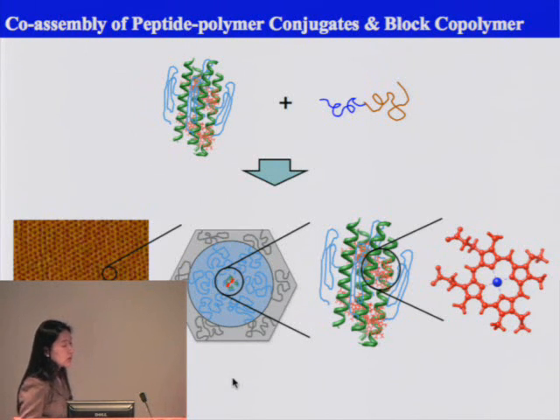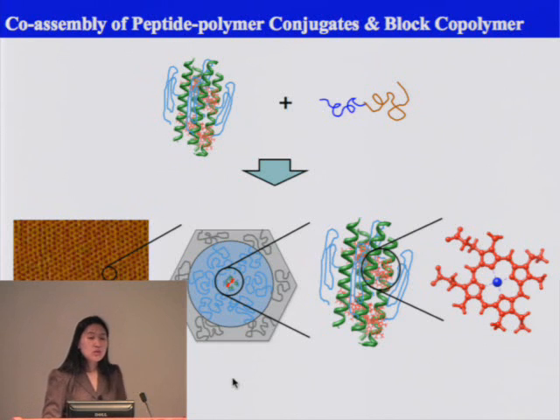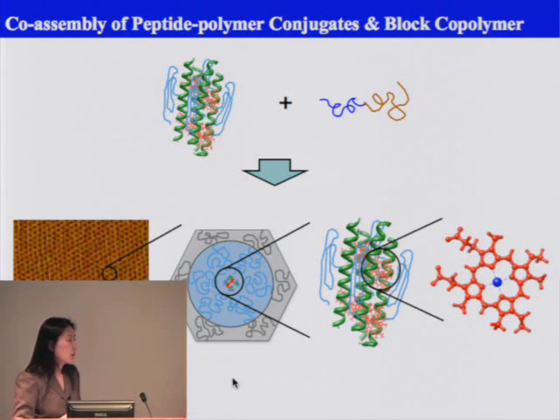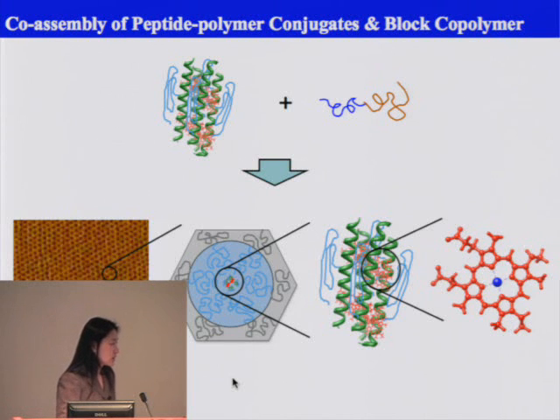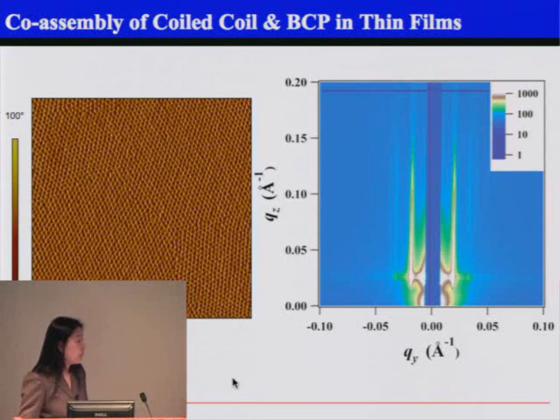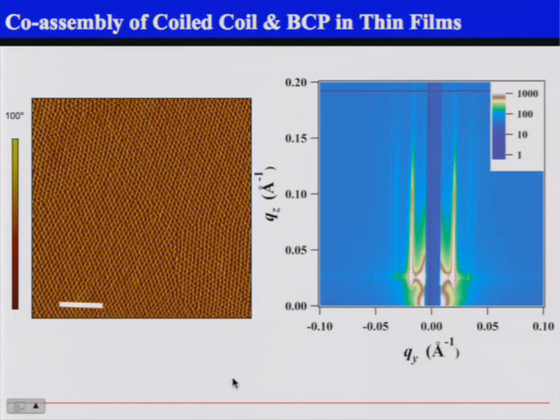In this case, we're interested in both light-induced charge separation and electron transfer, as well as enzymatic reactions - going from the cofactor to the peptide, and then co-assembling it with block copolymers. The take-home message is that even though these two systems are fairly remote from each other - one synthetic, the other biological - we can also order them into a very high density array.